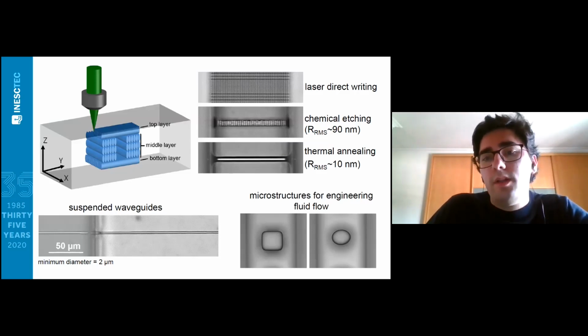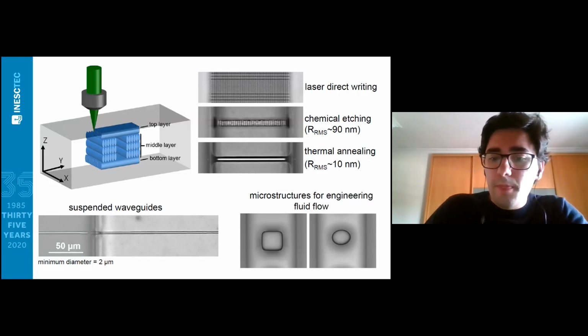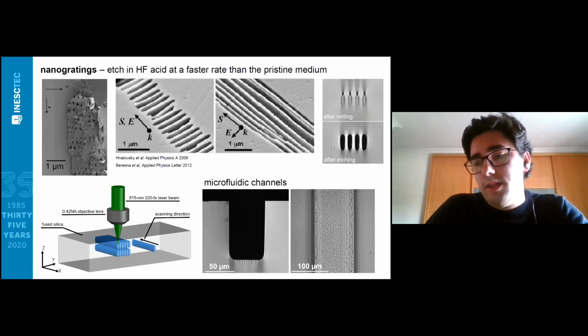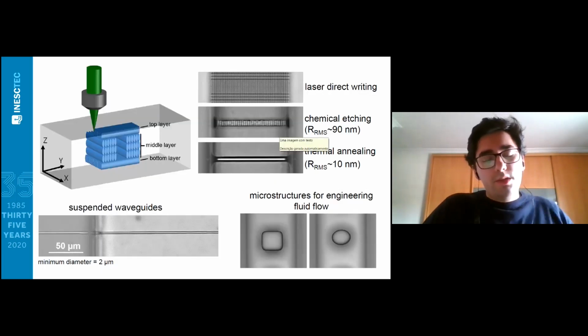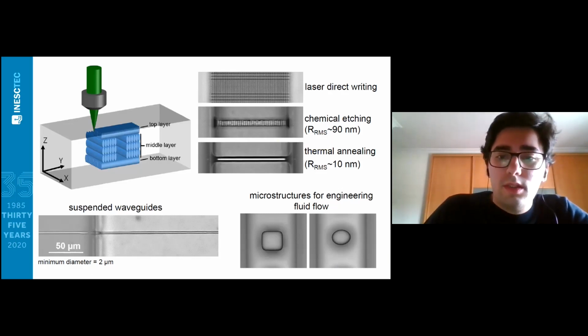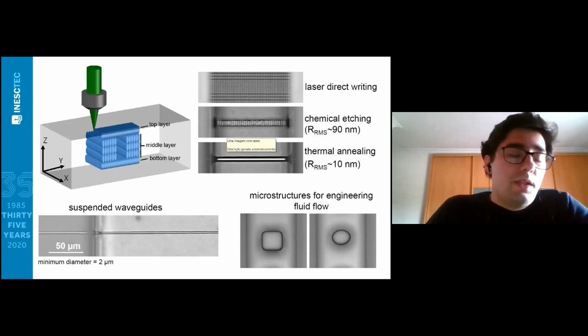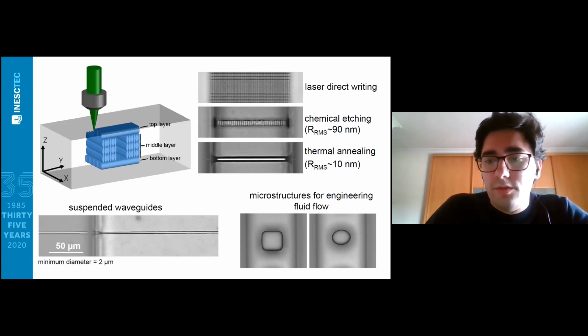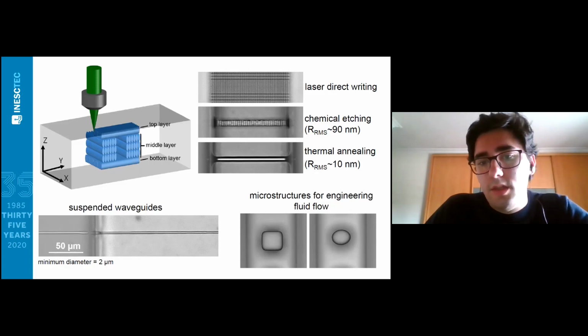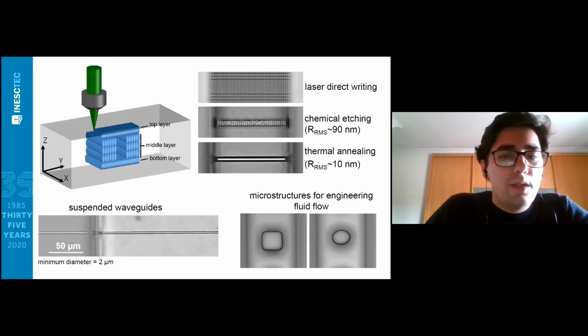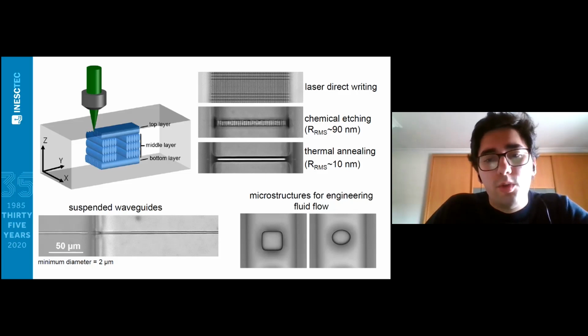One of the problems that we have, though, and this is actually a problem related to most glass machining processes, is that the surface roughness of this core is actually pretty high, and you saw that already in this top view image that shows the surface of the microfluidic channel. Because we have a high surface roughness, this can limit the application of these devices, as this can introduce optical scattering and really limit the application of the device for optical applications or for optofluidic applications. So what we then do to reduce this roughness is to perform thermal annealing at a temperature close to the glass point of fused silica, so it's around 1250 degrees, and we are able to reduce the surface roughness to around 10 nanometers, as you can see here, where we end up with a very smooth structure.